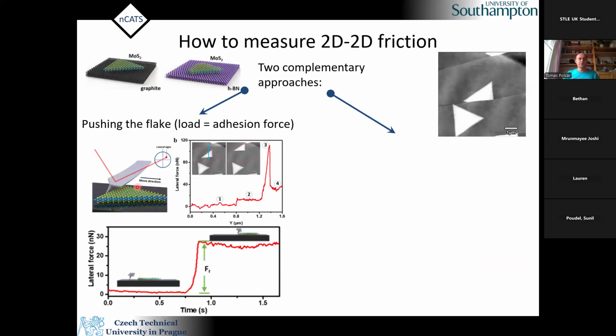When you put a flake, like this one, a very small flake of 2D material, on something like a very large flake, we said we can use an atomic force microscope in lateral force mode to push it. So we basically push this flake. And when we push the flake, we can measure friction, because we measure it really directly. There is no other effect than just the friction. That was the idea, and actually it works. And it works like that.